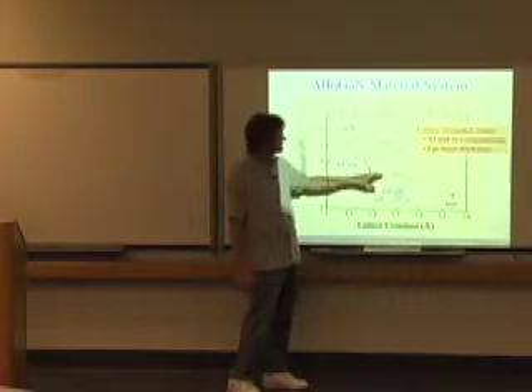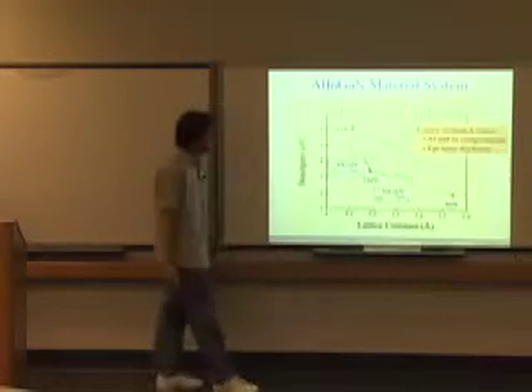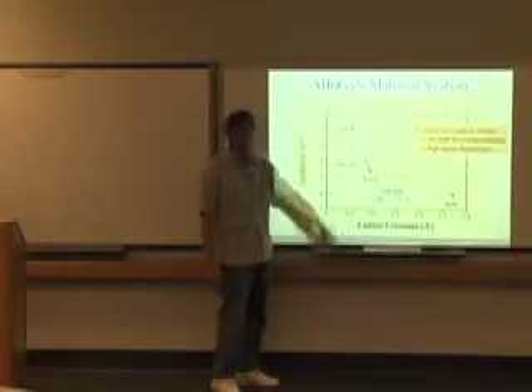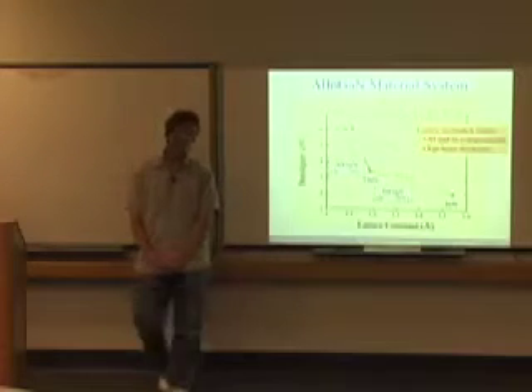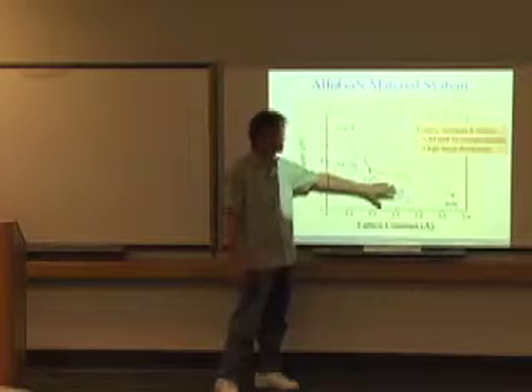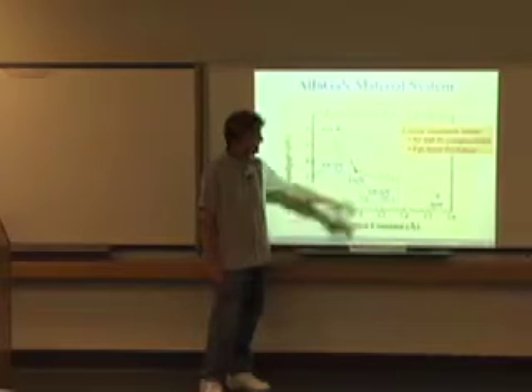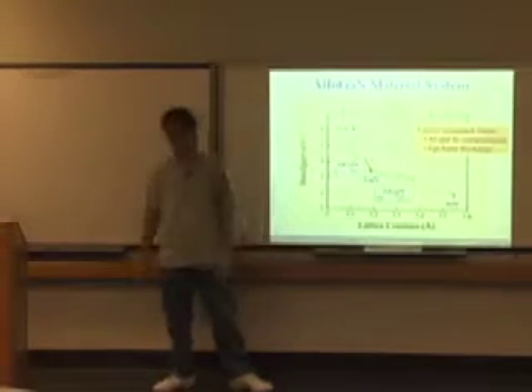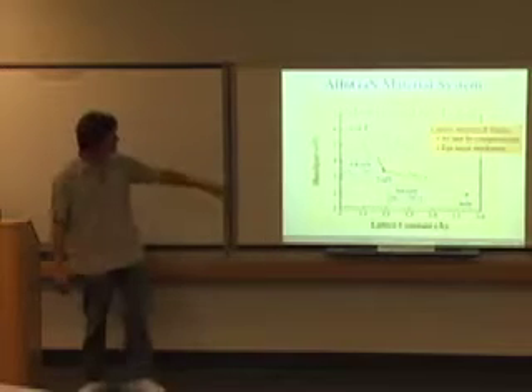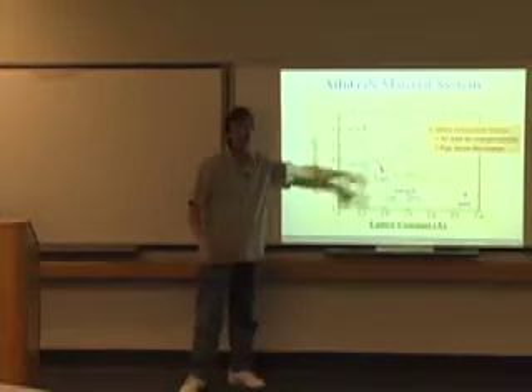And likewise, if you want to make the wavelength a little longer, you have to go along the InGaN line, which adds positive strain. Of course, it would be ideal if you could actually make a quaternary here, but no one at the time was very successful at making quaternaries. And the main reason is that the AlGaN is grown at very high temperatures and the InGaN is grown at lower temperatures. So there were just no good growth conditions for giving you very successful, good quality quaternary material. And so most people ended up using AlGaN to make the cladding layers. But you were pretty much limited to something less than 20% before strain caused a big problem.